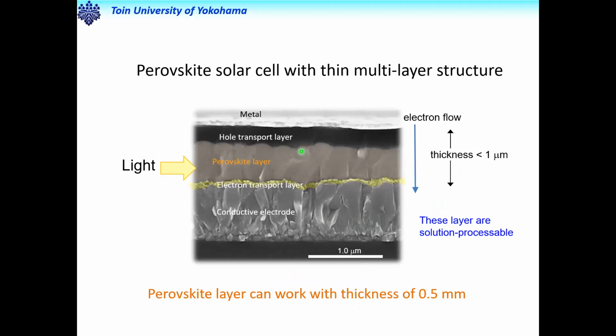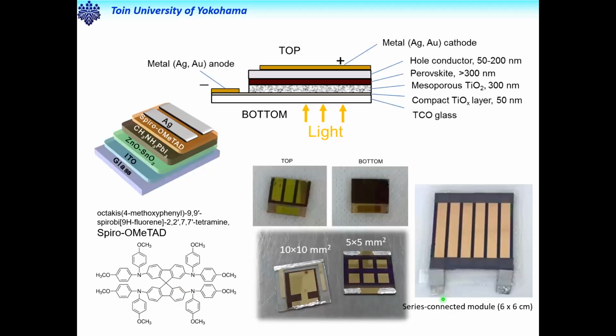Here's a sectional view of a perovskite solar cell. The perovskite layer is sandwiched between the hole transport layer and the electron transport layer. The absorber perovskite thickness is much less than 1 micron. So this is a typical thin film solar cell, like gallium arsenide. Based on this structure, we can make a very lightweight, flexible, thin film solar cell. So the perovskite layer can work with a thickness of around 0.5. Sorry, this is a mistake. 0.5 micrometer.